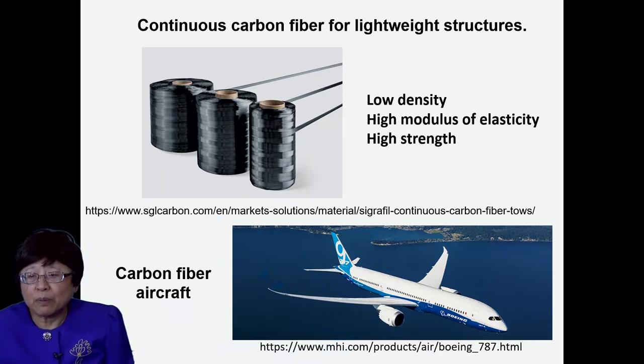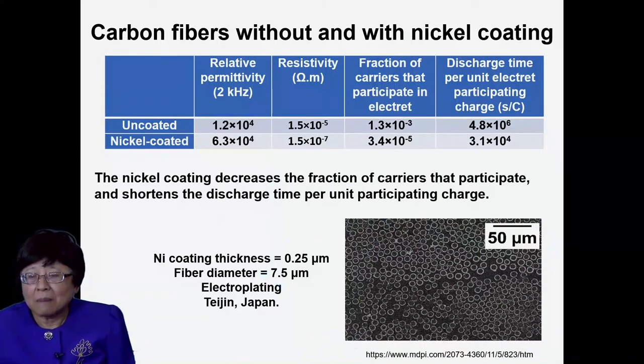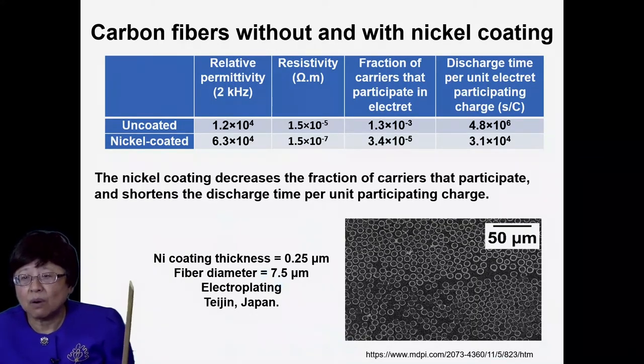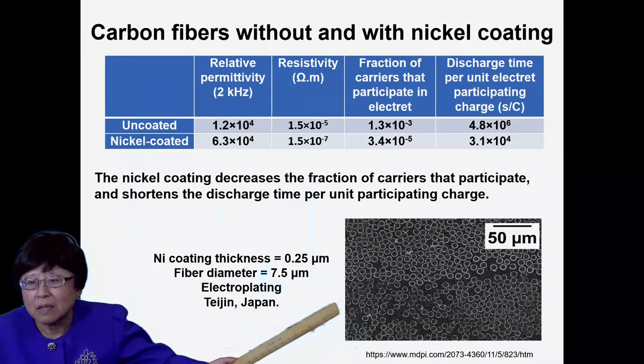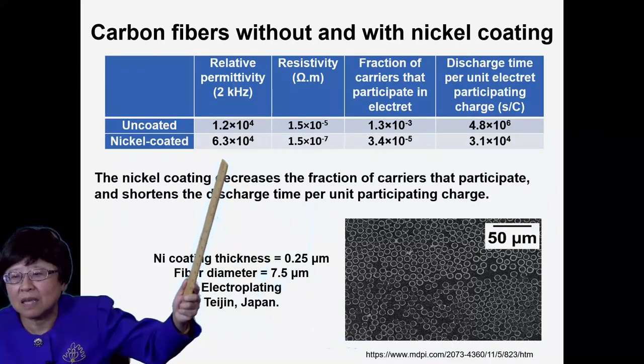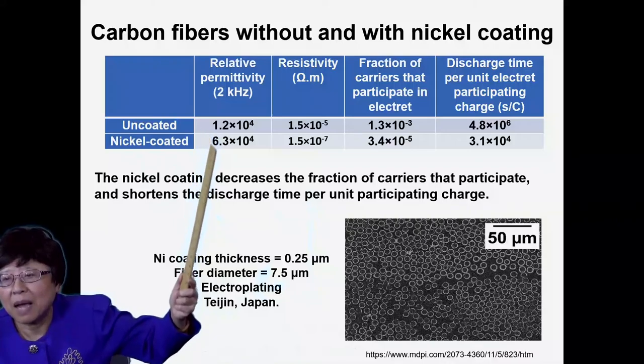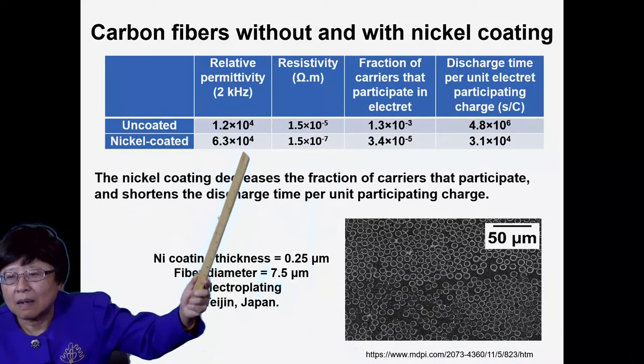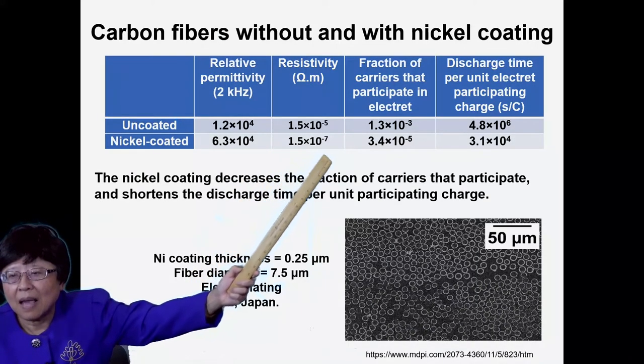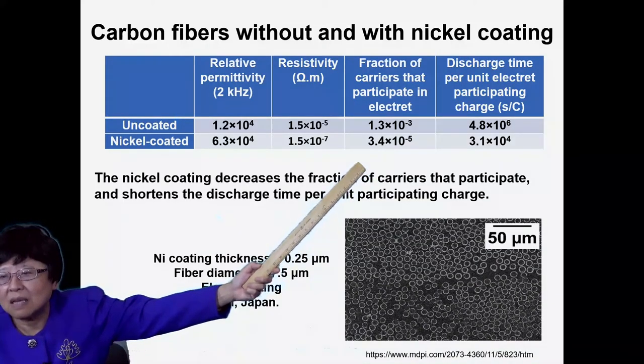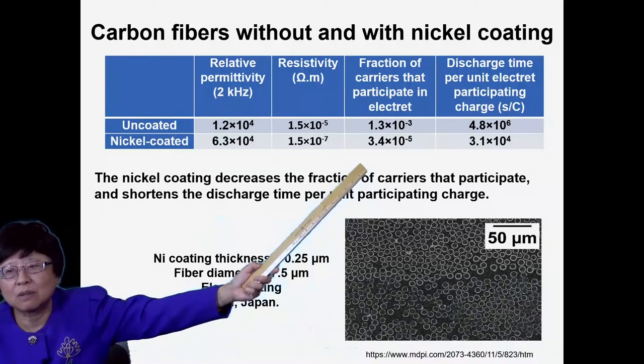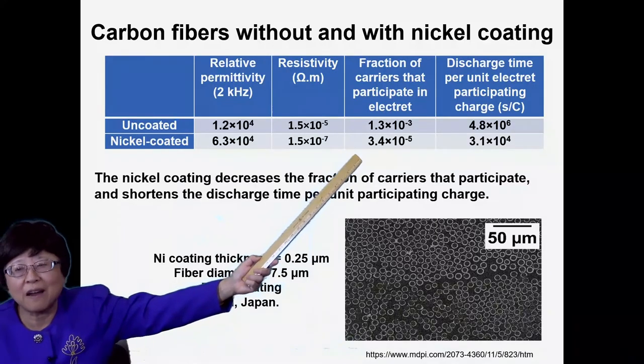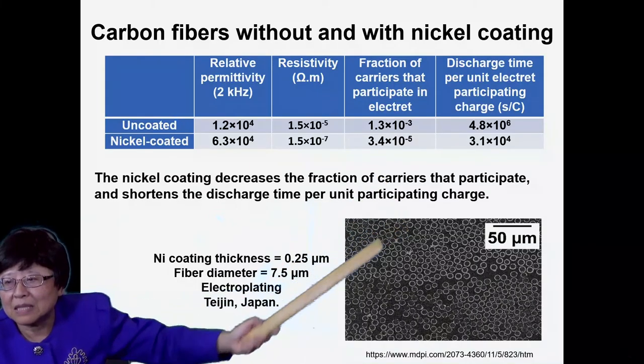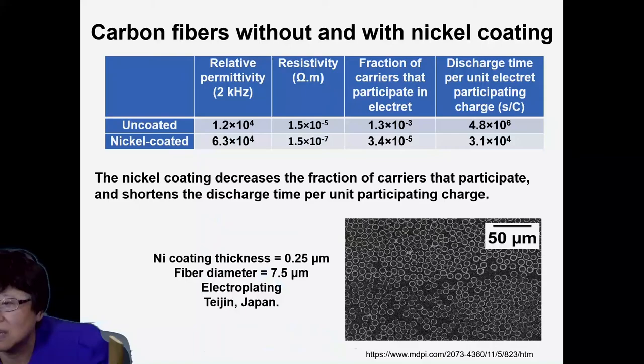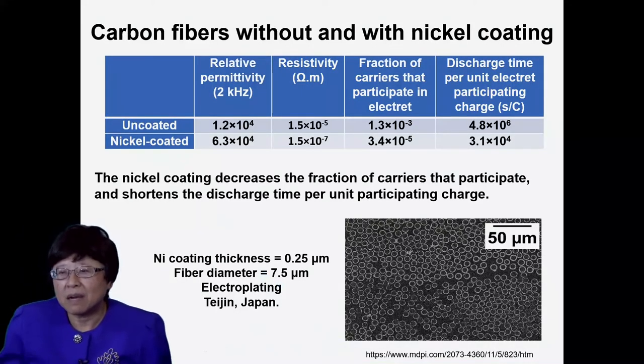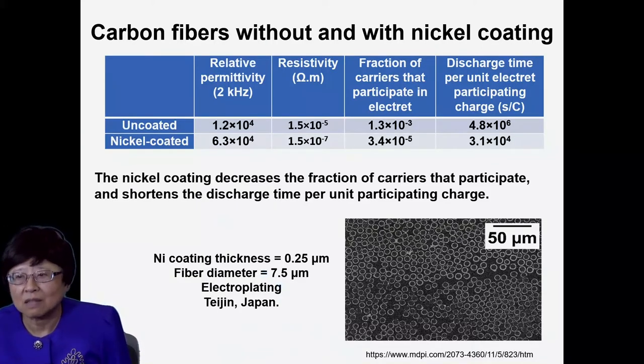Now, continuous carbon fibers are very important for lightweight structures such as aircraft, and we have looked at the carbon fibers without and with nickel coating. This is the cross section of the nickel-coated carbon fiber, and you can see that the permittivity is increased a lot by the nickel coating. The resistivity is decreased a lot, and the fraction of carriers that participate in the electret is decreased by the nickel coating, because the metal coating has a lot of free carriers, making the denominator big. But the discharge time constant per unit electret-participating charge is much decreased by the nickel coating because of the nickel providing high conductivity, making the discharge faster.